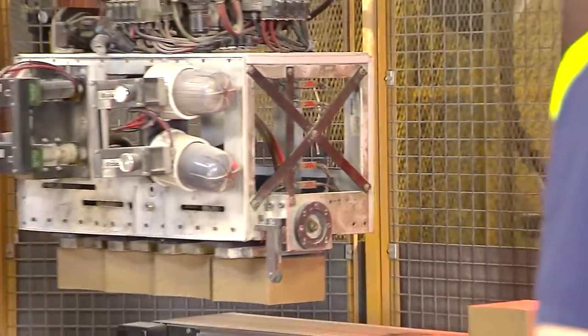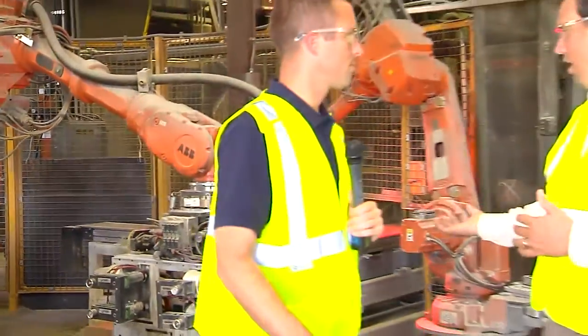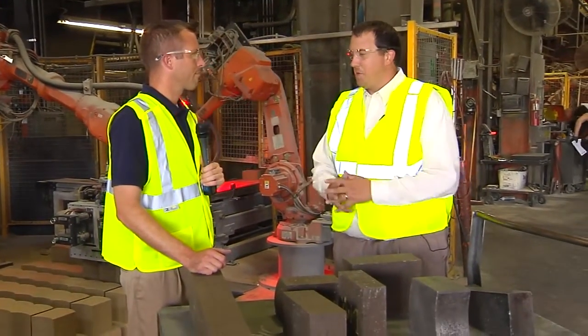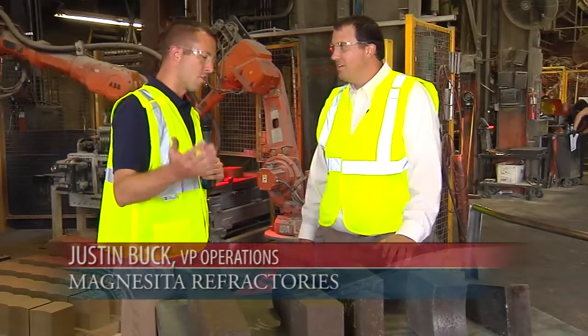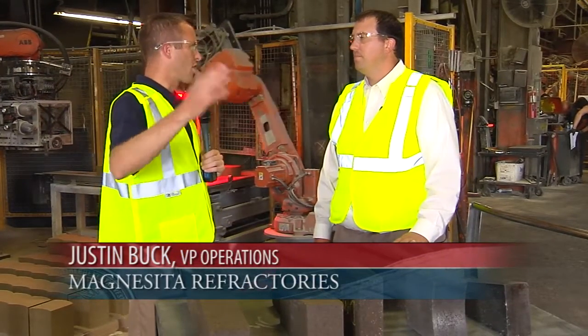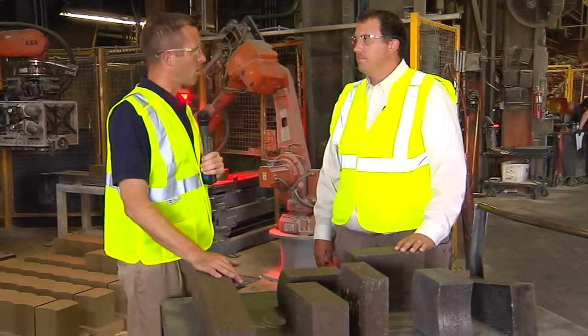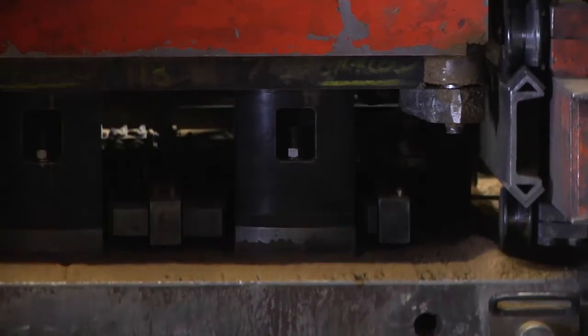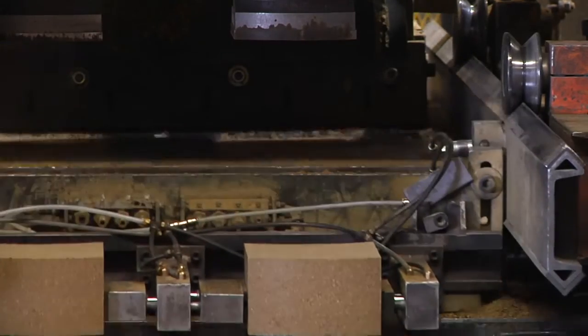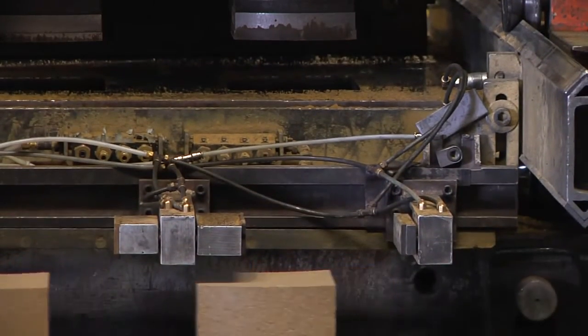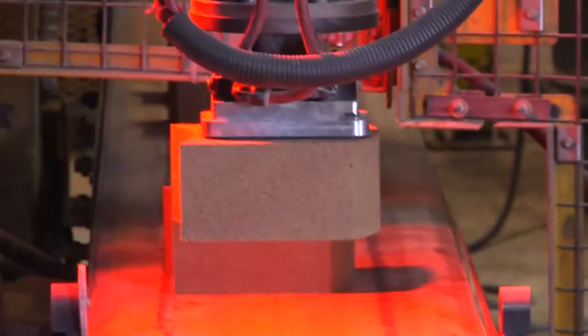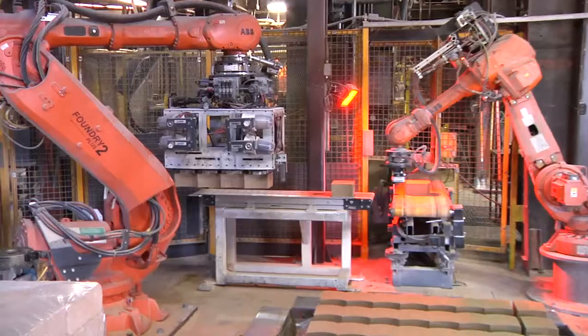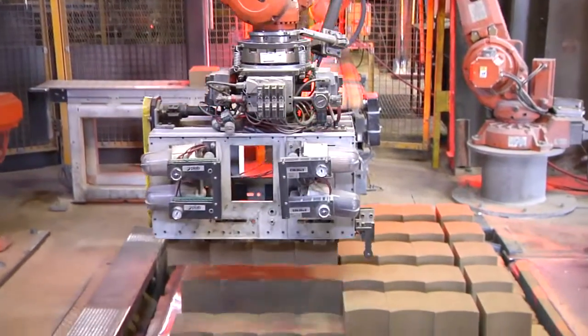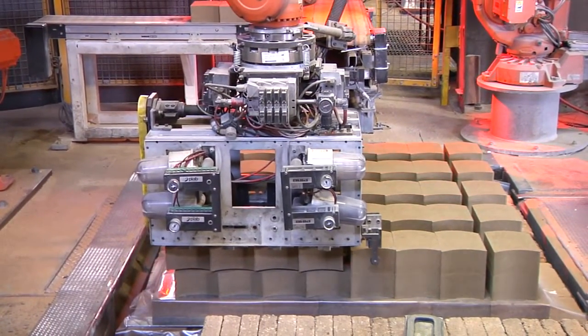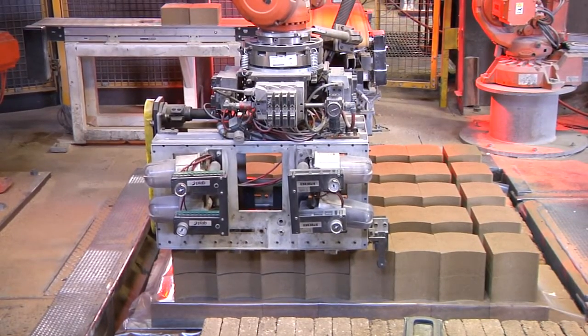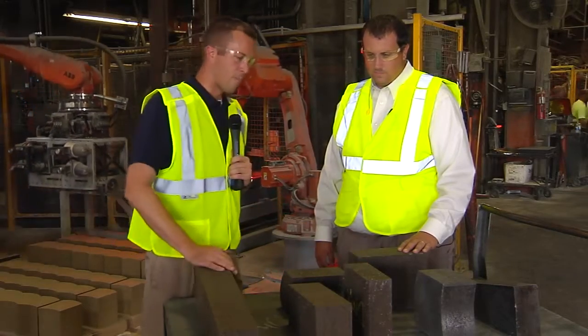All right, so here we are in the brick manufacturing. We have some awesome new technology behind us. Kind of explain what's going on in your products. Okay, so the sintered dolomite, as well as sintered magnesia that we bring in from our sister plant in Brazil, and some other additives are mixed together with an oil-based binder, pressed into these brick shapes by the presses that you see behind us. We have 9 presses. The bricks are pressed at pressures up to 2,000 tons, so very high pressure pressing. They're stacked on kiln cars and racks by the robotics that you see behind us, and fired in tunnel kilns and an oven. This family of bricks here, these are fired dolomite bricks.